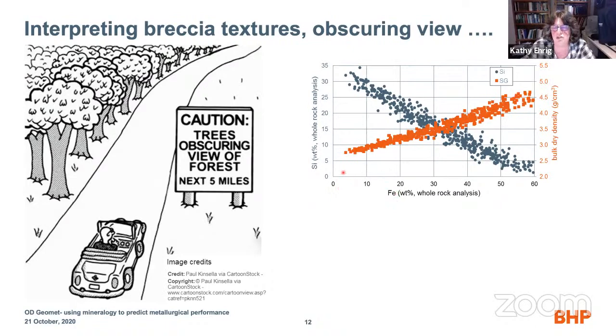in the iron concentration, starting out in fresh granite, going all the way to the center. With that, we also have silica and 30-plus other elements, and even up to almost the whole periodic table. And what we see is there's a whole suite of elements that, as the iron content increases, so do some other elements, mainly the hydrothermal elements. But as the iron content increases, the granite really is being stripped away. So really all the primary elements in that granite gradually get depleted.